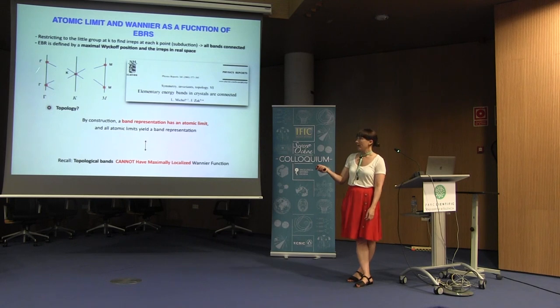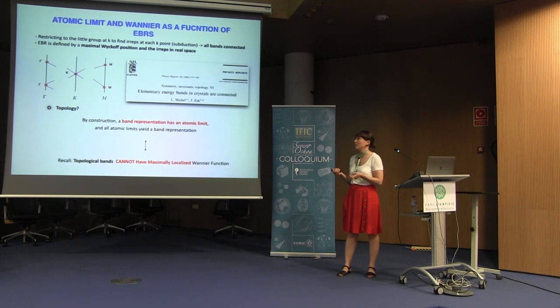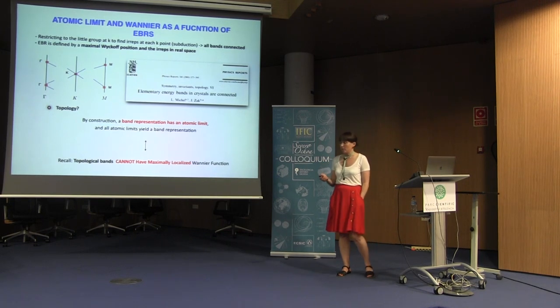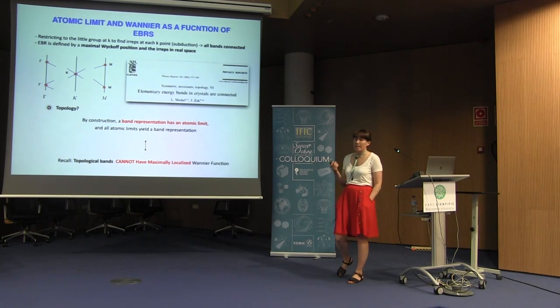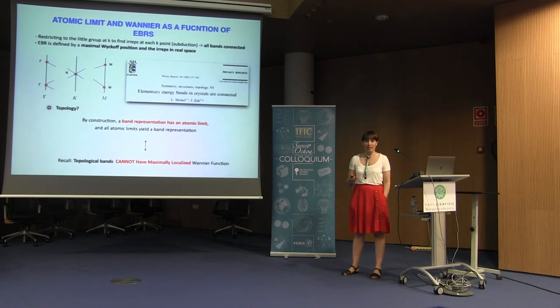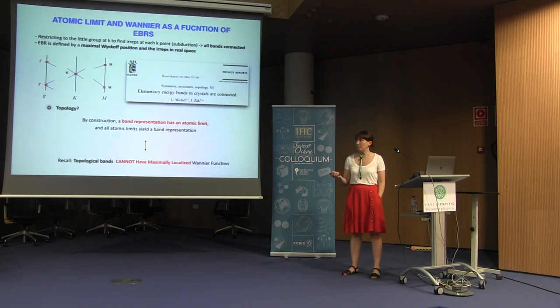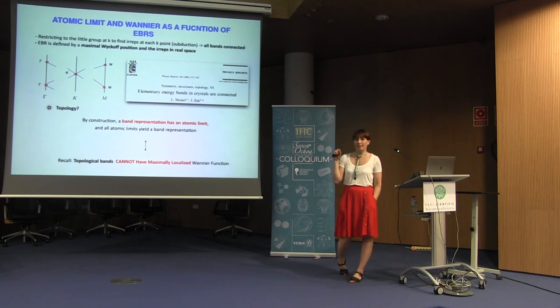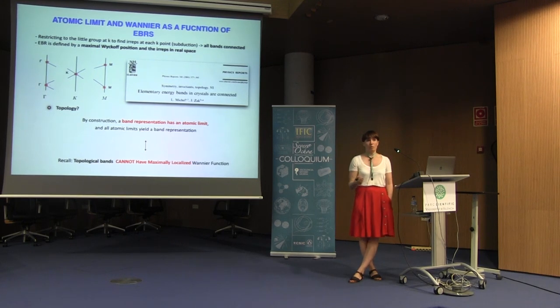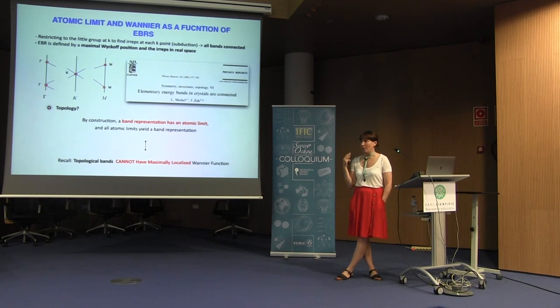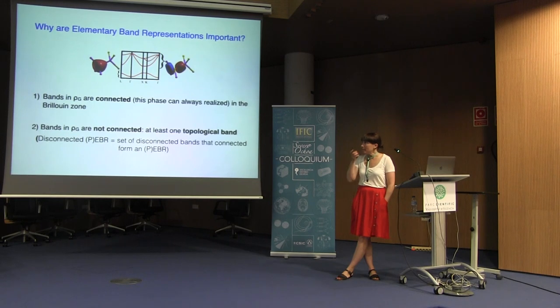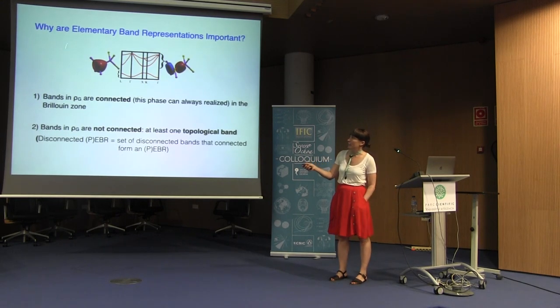I'm in reciprocal space with these little groups here, but I know they have to be connected. So what is the relation of this that I'm talking about with topology? Well, the relation comes from a paper of Zak and Michel already back in 2000, where they claim that elementary energy bands in a crystal always need to be connected. And this is true as far as the bands are not topological, as far as the topological order is zero. Because, as I said before, this induction of bands has been done in the atomic site. And therefore, the atomic limit is respected. And the topological bands do not respect the atomic limit, because otherwise there would be no charge flow on the edges.